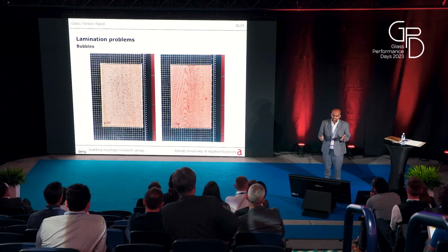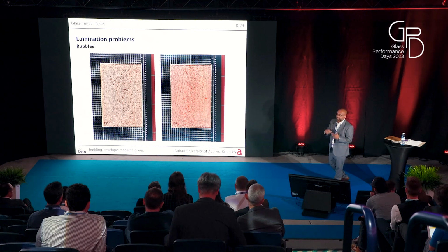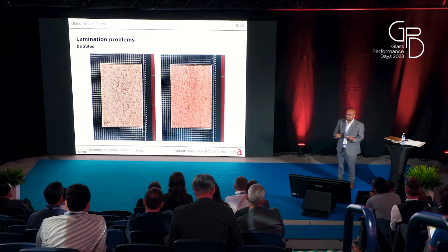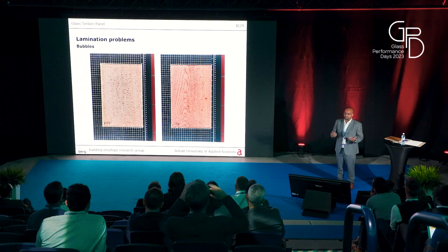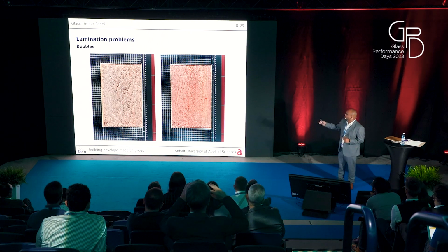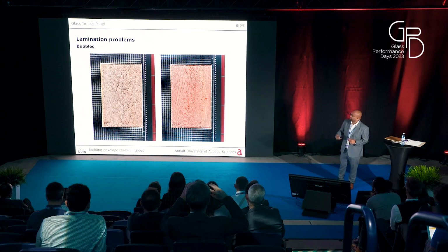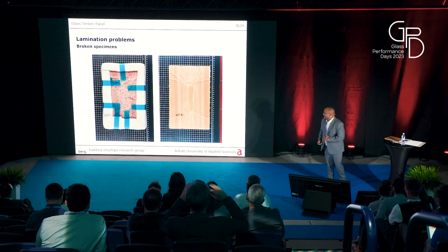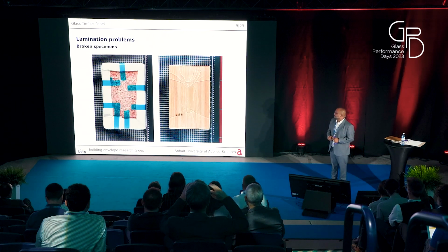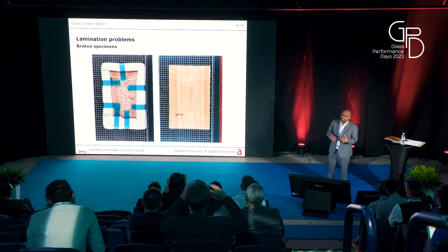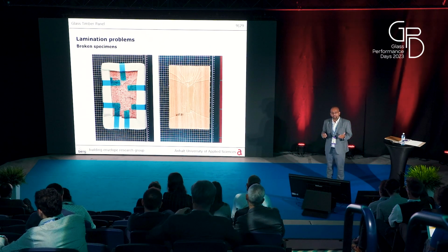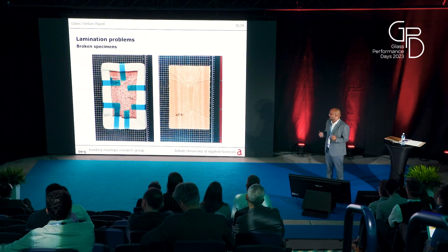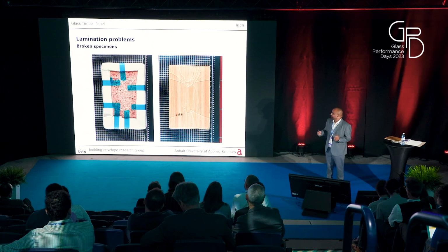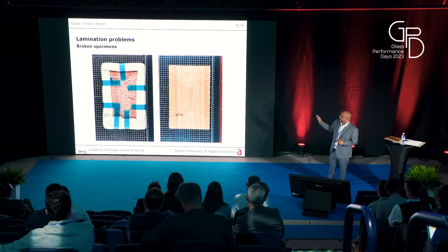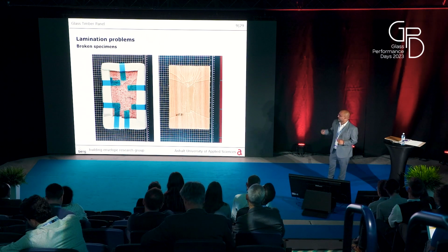When we use the same lamination process for glass, the heat transfer is better for glass than for wood. So we had to increase the heating time for the lamination, and we did get better results. Sometimes we also had some broken glasses, mostly with thicker foils. We also made tests on 1.52 millimeter layers, and mostly all the specimens laminated with thicker foils tended to break.